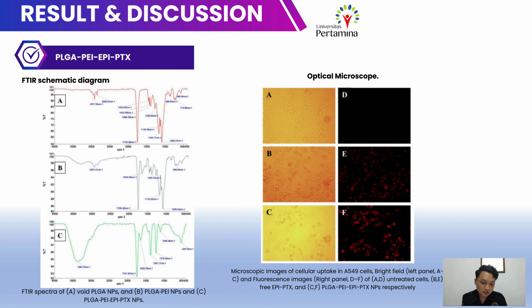FTIR was used to analyze the chemical interaction between nanoparticle components. The FTIR test results show a shift in the absorption peaks indicating the interaction between PLGA, PEI, EPI, and PTX, which changes the absorption peaks of the C=O and C-O bonds. In addition, absorption peaks indicating the formation of secondary amide bonds were also detected, indicating chemical interaction between the nanoparticle components.